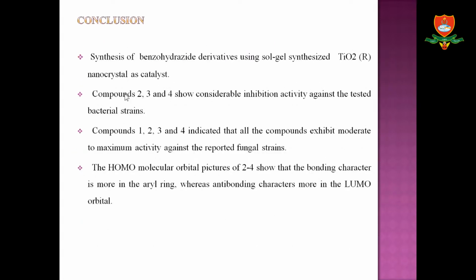Conclusion. So, synthesis of benzoyl hydrazide derivatives using sol-gel synthesized titanium dioxide nanocrystal as catalyst. Compounds 2, 3, and 4 show considerable inhibition activity against the tested bacterial strains. Compounds 1, 2, 3, and 4 indicate that all the compounds exhibit moderate to maximum activity against the reported fungal strains. The HOMO-LUMO orbital pictures of 2 to 4 show that the bonding character is more in the aryl ring, whereas the anti-bonding character is more in the LUMO orbital.